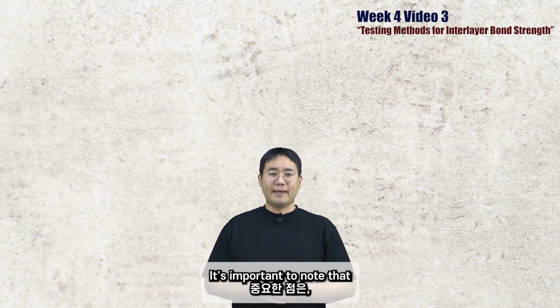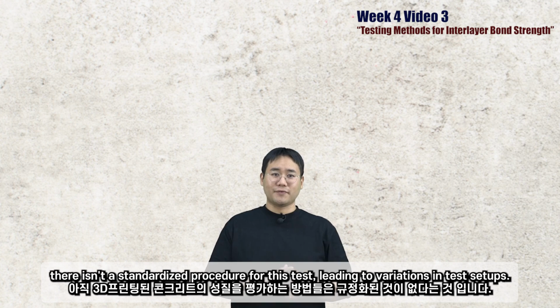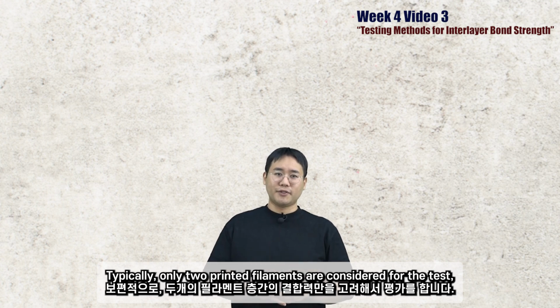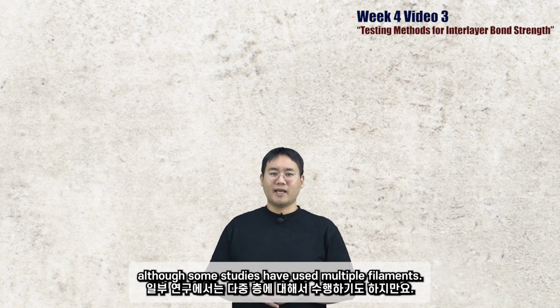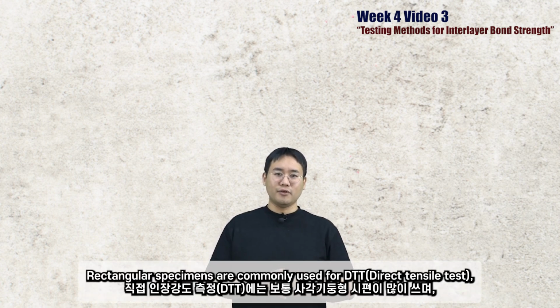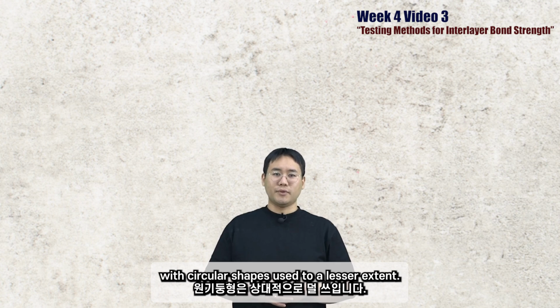It's important to note that there isn't a standardized procedure for this test, leading to variation in test setups. Typically, only 2 printed filaments are considered for this test, although some studies have used multiple filaments. Rectangular specimens are commonly used for direct tensile tests, with circular shapes used to a lesser extent.